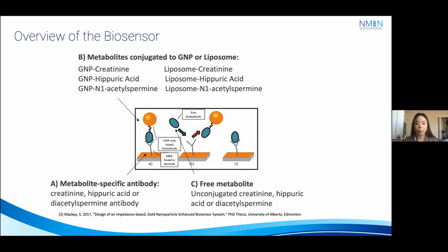So in this project, we had 6 conjugates prepared, and those conjugates are able to bind to the antibody via the metabolite attached to its surface. And then finally, the free metabolite of interest, which should have a higher binding affinity to the antibody, is able to displace the conjugated nanoparticle. And the release of this nanoparticle should then cause a decrease in impedance or a reversal of the effect caused by the initial attachment.